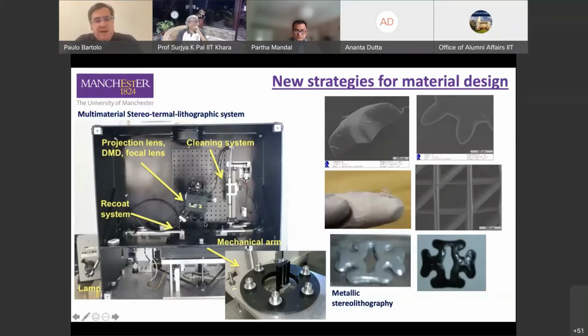Then we have a reduction lens here to transfer the image created in the DMD into the reservoir. This reduction lens reduces the image projected on the DMD by 10 times. So if you consider that each DMD has small micromirrors of 40 micrometers by 40 micrometers, this means that we can create an image on the surface of the resin with a size of 4 micrometers by 4 micrometers.